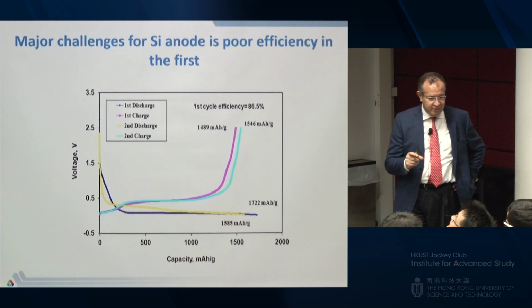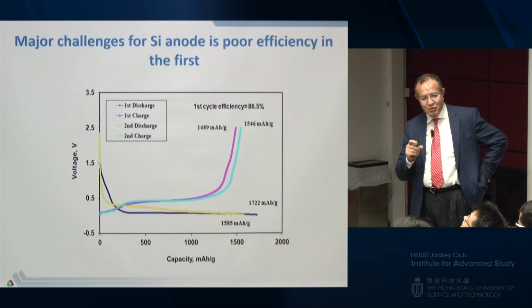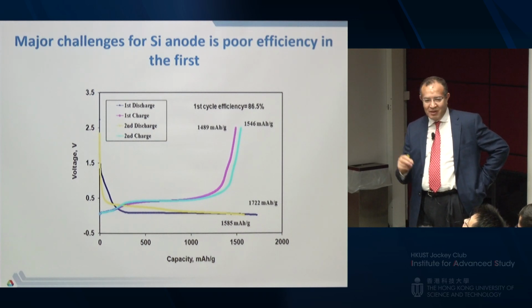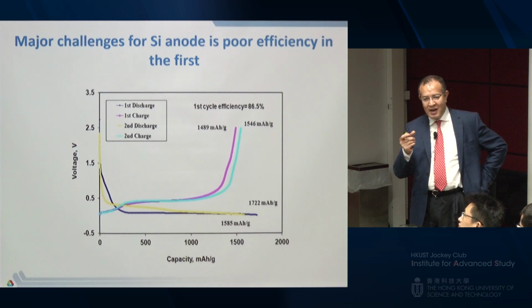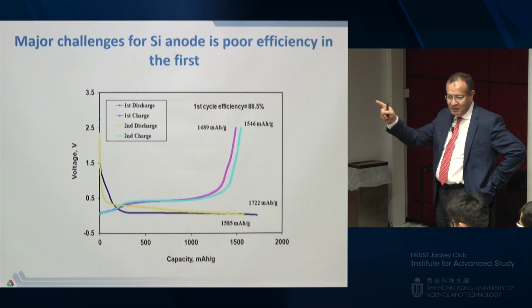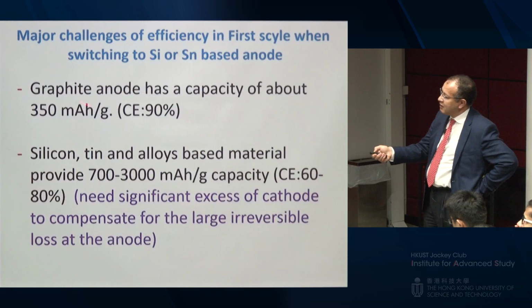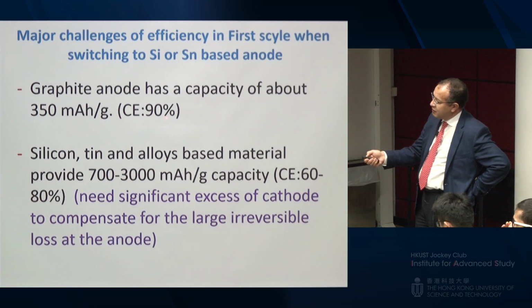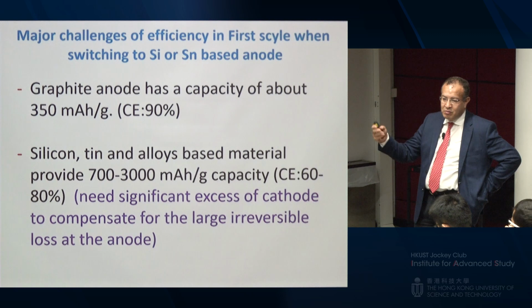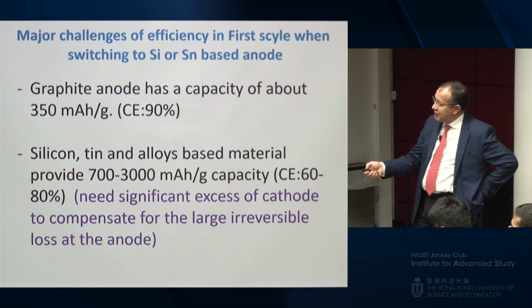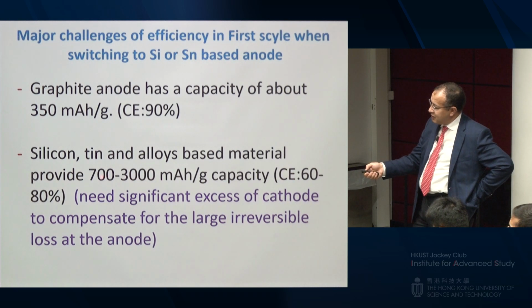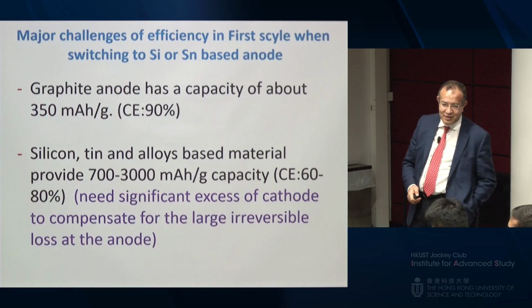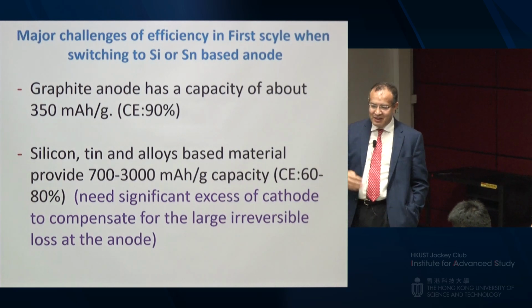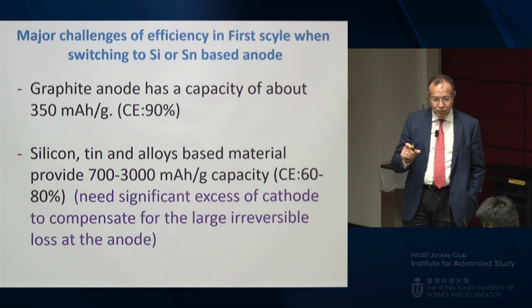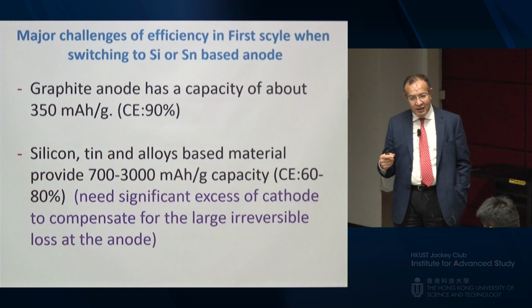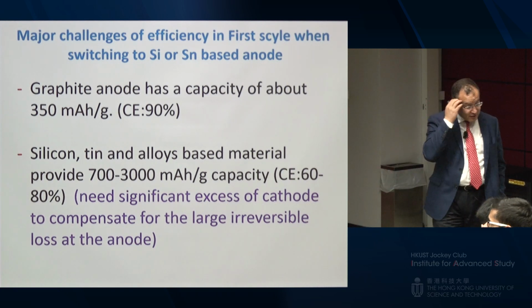If you use the concept of carbon, carbon is about 98% efficiency, and is only 360 milliampere hours per gram. So 2% out of 300, you can easily design an excess amount of cathode to take care of that irreversible loss. Here it is. In the case of graphite, it is 90%. So it's okay to use excess cathode, the lithium, to compensate for that irreversible loss. But in case of silicon, the capacity can vary between this, and the efficiency is low. There is no way you can use a large amount of cathode. You need pretty much double the capacity of excess cathode just to compensate for the first irreversible loss. So cathode is expensive and heavy, so your overall energy will drop significantly. So that's not a way to go.